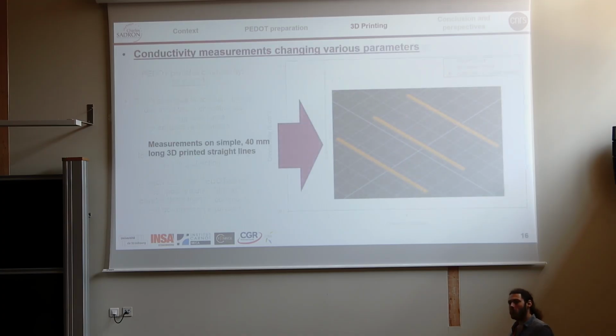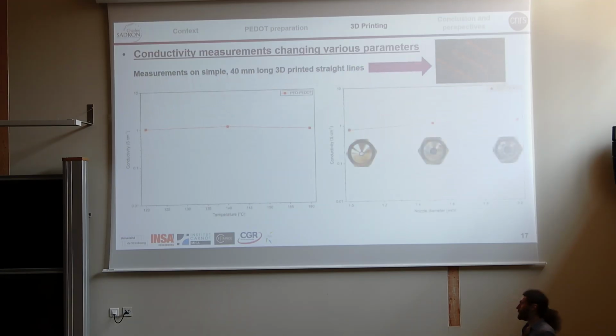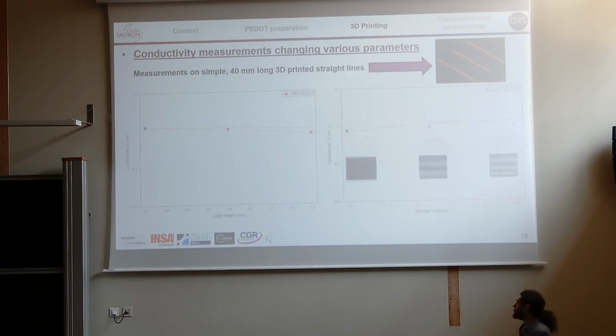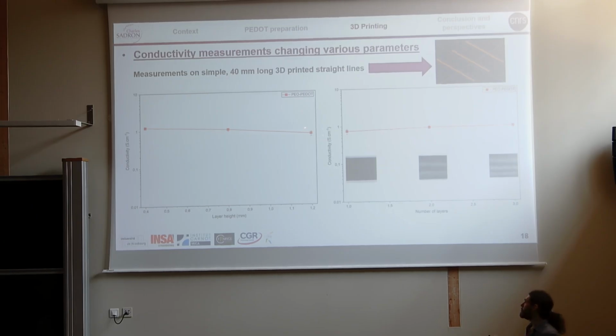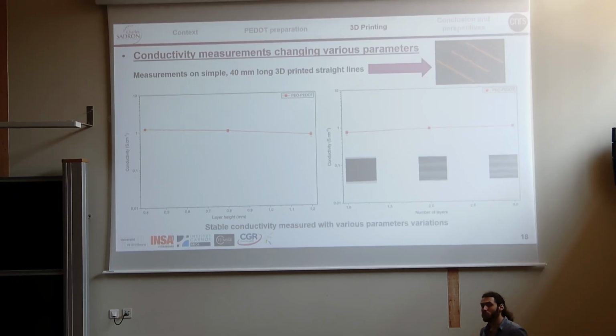Next, I decided to conduct additional measurements on straight lines that were printed by varying several other parameters. So, for example, the temperature and the nozzle diameter. And you may notice very small variations, but you can still see that the conductivity remains around 1 Siemens per centimeter. And you will have the same results when changing the layer height or the number of layers for a same sample height. You just have a little change in the values that is too small to be considered significant at this point. So it proves that we have a very stable conductivity even while changing the transformation parameters.